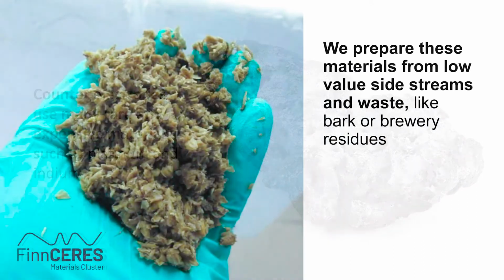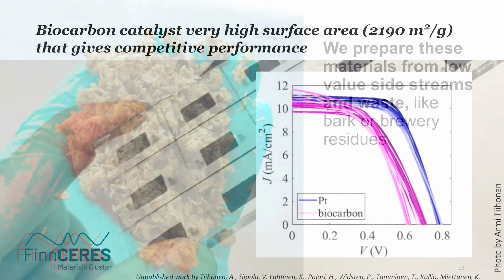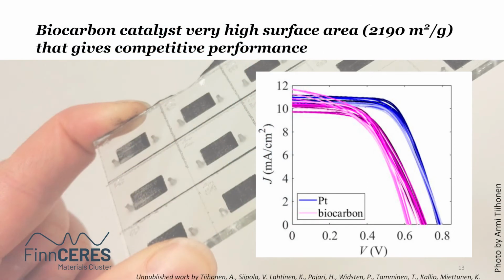In this project, we prepared bio-based carbons utilizing low-value side streams or waste. We tested, for instance, brewery residues, and we are currently investigating utilization of wood bark as the biocarbon. The interesting fact with the biocarbon catalyst was that we could get much higher catalytic surface areas compared, for instance, to fossil-based carbons. On average, those were 4 times higher with this material compared to the fossil carbons.